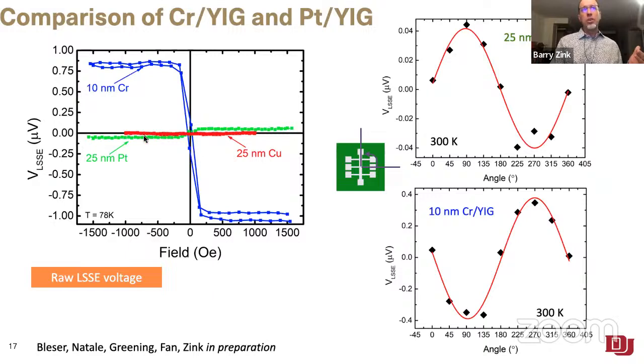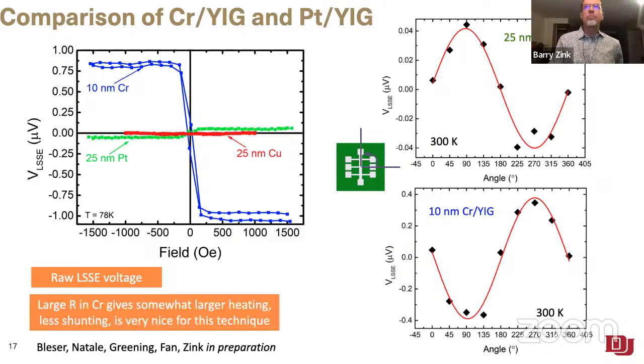That's a 25 nanometer thick platinum, which is probably too thick. You're shorting out the effect you're trying to generate a little bit there. So it's certainly not optimal, but it is a clearly resolvable signal. In a copper film about the same thickness, we don't see any clearly resolvable signal. That's nice. I'm used to thinking that copper should be my zero reference for this. I know that there's a question now about other types of interesting angular momentum effects in copper. So for the moment, it is providing a zero for these experiments for us anyway.